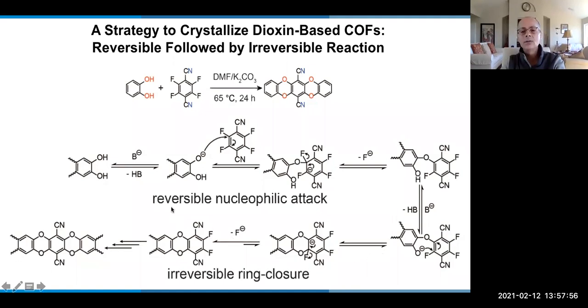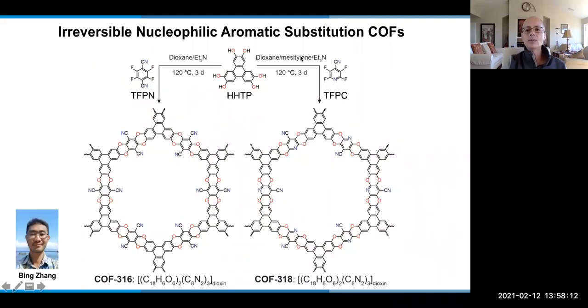And so what I'm trying to say is that the irreversible linkages can be crystallized by preceding that with a reversible linkage that brings the components very close together. And then in the end, as we show here, the ring closure reaction. So that's the conditions under which these dioxin-linked structures form. These are the crystal structures from powder diffraction.